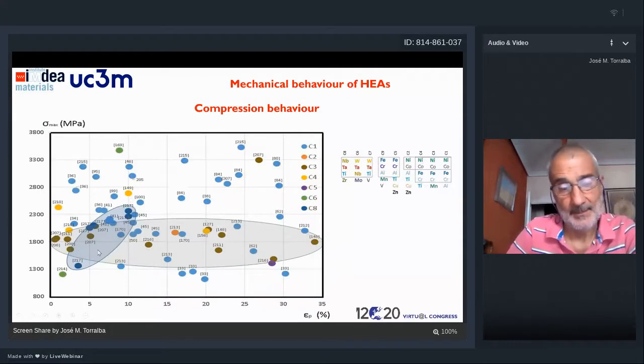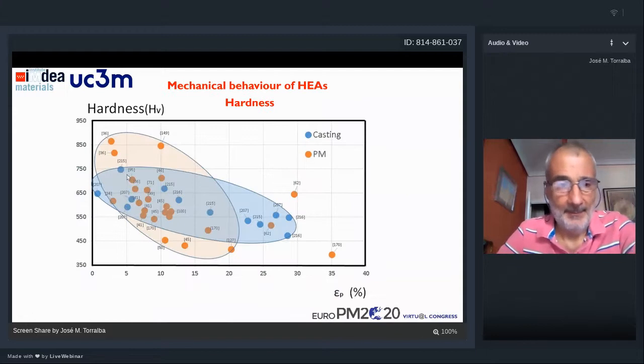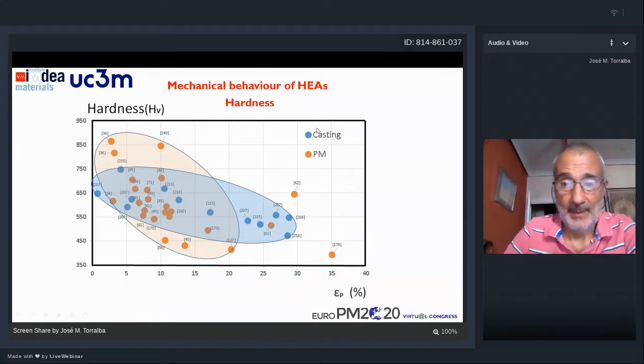We have most of the transition metal high entropy alloys, and in this horizontal zone we have the papers that have used the Cantor alloy. So with the Cantor alloy we have a lot of possibilities to get different kinds of properties for different applications. So in this graph we can compare the hardness against the ductility in both high entropy alloys produced by ingot metallurgy and high entropy alloys produced by powder metallurgy, in orange.